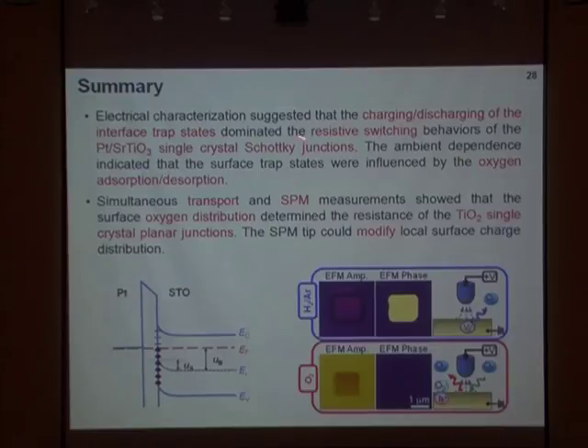But I can say something like this: this kind of switching is mainly due to trap states, more like an electronic process. That corresponds to some ignition process in thin film switching. Once this kind of switching can occur, it can form a conductance chain, and as a result, joule heating can occur, which will accelerate the migration of oxygen vacancies along the defects of thin film devices.